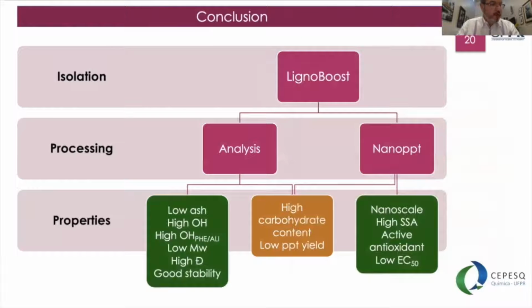With this, we hope to have demonstrated that nanoparticles could be produced by nanoprecipitation from this LignoBoost eucalypt Kraft lignin without any further purification, and that the material obtained, regardless of its relatively high carbohydrate content, had a tremendous performance compared to one of the best reference materials available in the market.